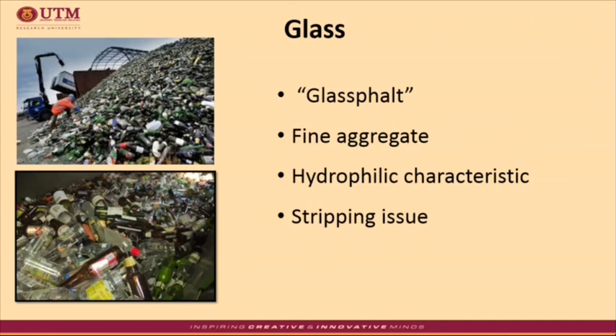The waste glass is crushed and screened and then used as a portion of fine aggregate, between 10 to 15% in wearing course. However, the use of more than 15% of waste glass can cause stripping problems to the asphalt binder. A previous study also found that glass can be used up to 25% for base or binder course. The glass doesn't absorb the bitumen, which makes it hydrophilic in characteristic. However, it is prone to moisture damage, which can cause stripping and raveling problems due to loss of adhesion.